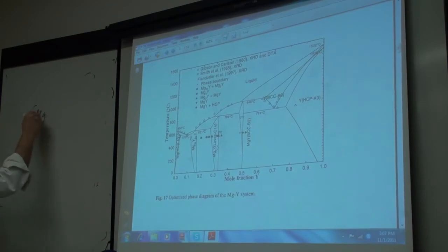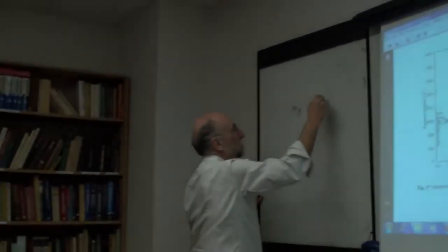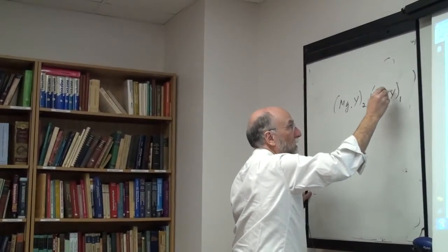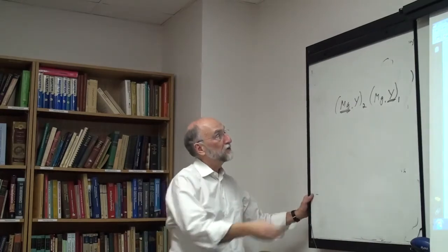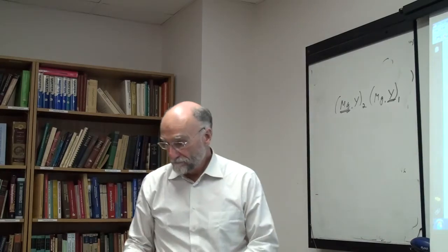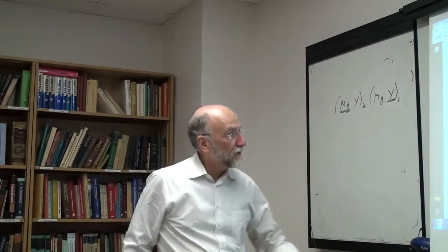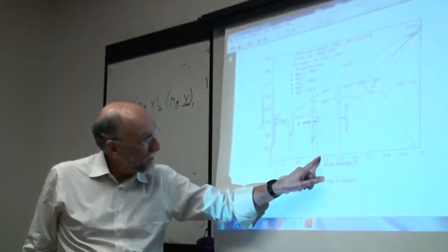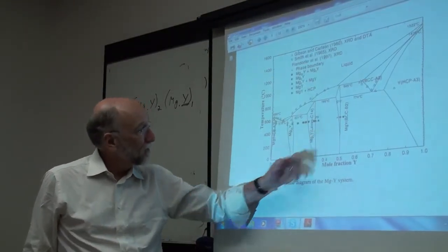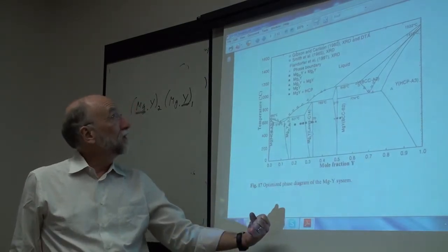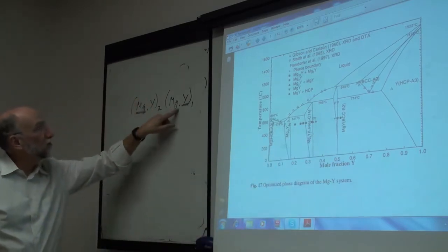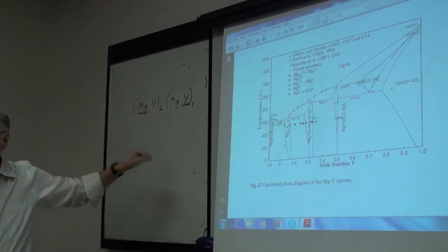We would write (Mg,Y)2(Mg,Y)1. This is mainly occupied by magnesium. This is mainly occupied by yttrium, but you can get some yttriums over here and you can get some magnesiums over here. And that's why you get the non-stoichiometry. It's clearly more over to this side, 33% is around here. Which side is magnesium? This is magnesium. You're clearly getting excess magnesium, so you're getting more magnesium on the yttrium sites than yttriums over here.